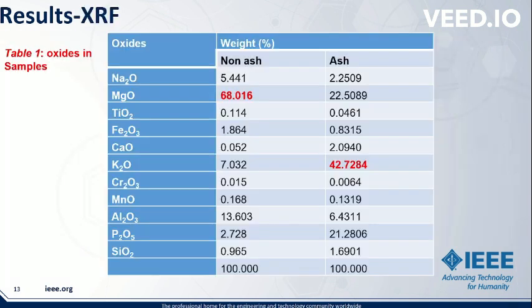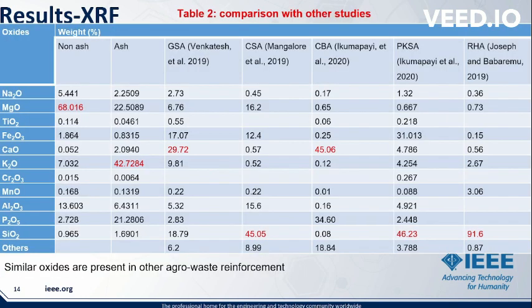The quantitative analysis showed that sodium oxide, magnesium oxide, titanium oxide, iron oxide, calcium oxide, potassium oxide, chromium oxide, manganese oxide, aluminium oxide, and so forth were present in both non-ash and ash samples. Magnesium oxide was the most predominant oxide in the non-ash sample, while potassium oxide was the most predominant oxide in the ash sample. Comparing this with that of other studies, similar oxides are present in other agro wastes that have been used in fabricating or synthesizing aluminium composites.